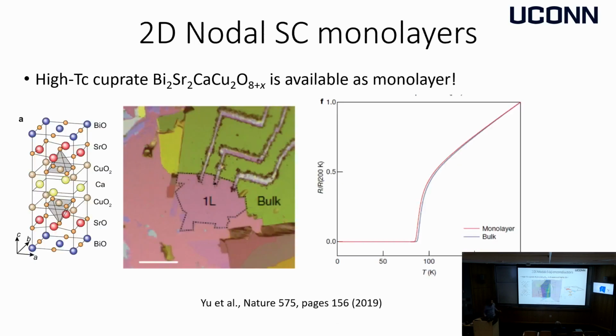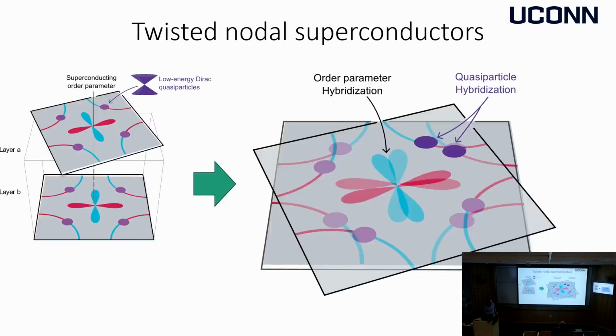The other motivation comes from the fact that precisely the same material, being one of the most two-dimensional of the high TC cuprates, is to a certain extent exfoliable. It's not as easy as with graphene, but already in 2019, it has been realized that you can take one monolayer of this material, which actually contains, for details, two superconducting planes rather than one. Well, that's crystallography, but it's still a single unit cell thick layer of that material, and it superconducts, and you can almost see no difference between superconducting properties of the monolayer and the bulk. Okay, so I've introduced two basic elements.